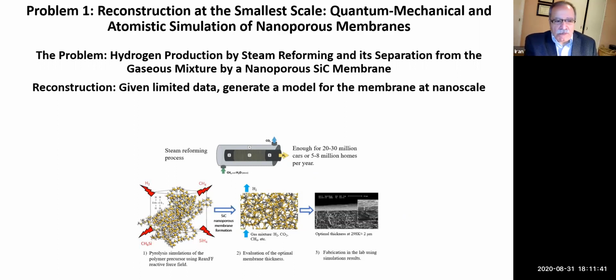So the way it's done is basically the way we developed the model. We wanted to optimize the performance of this, and the way it's done is we have a polymeric precursor. It goes under pyrolysis. It loses all the atoms such as nitrogen, oxygen, and so on, and at the end you are left with silicon and carbon. And then silicon and carbon react with each other and form a silicon carbide amorphous material, which is a membrane layer on top of the support. The support, I'm showing it on the right, so the support is another silicon carbide porous material, except that it has a meso scale, so it cannot be used for separation. And then you deposit that membrane layer of silicon carbide on top.